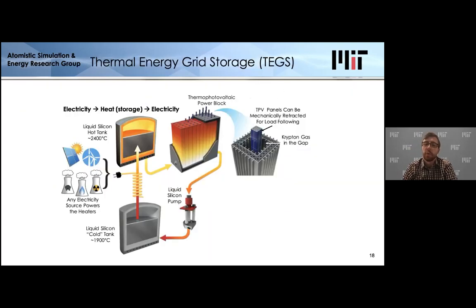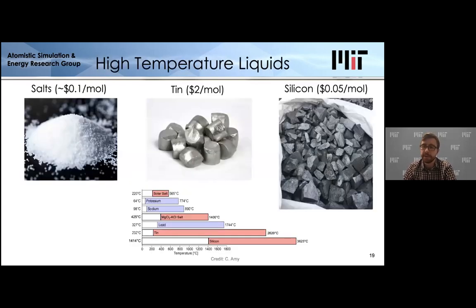So you may be asking, well, why are we using silicon in this application? And there's a number of reasons for that. The primary one is that silicon is really, really cheap. So salts are inexpensive. Tin is significantly more expensive, but has better heat transfer performance. Silicon actually has a very similar heat transfer performance to tin, but at a cost even lower than that of salts.